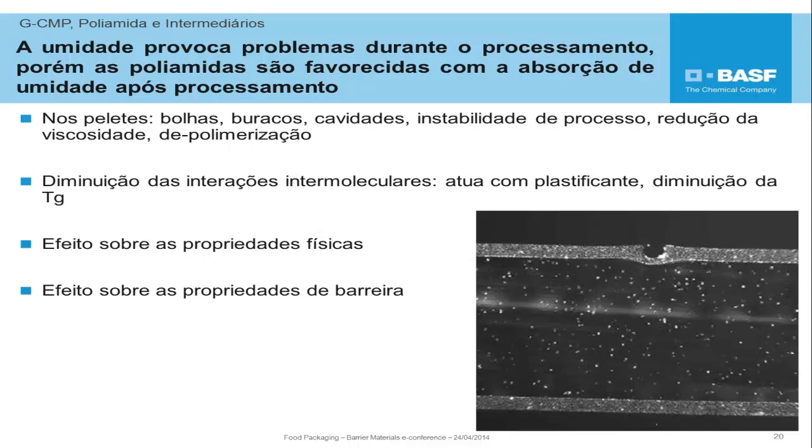And according to the picture on the slide, we can also have problems in extrusion as cells or balls of humidity form. While that ball of humidity occurs, a true rupture of the coating material will possibly end up giving a breakdown of the film as a whole during extrusion. That would thus render it useless. Obviously, these are negative effects of humidity that should always be avoided.